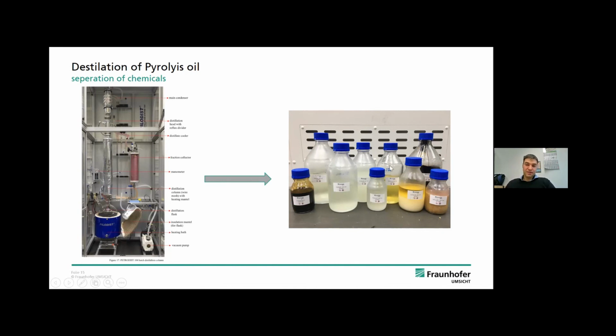However, our target is to go into higher purities, and the amount of halogens in these chemical fractions at the moment is lower than 100 ppm, and our target is to lower this also to less than 50, or target is 10 ppm.